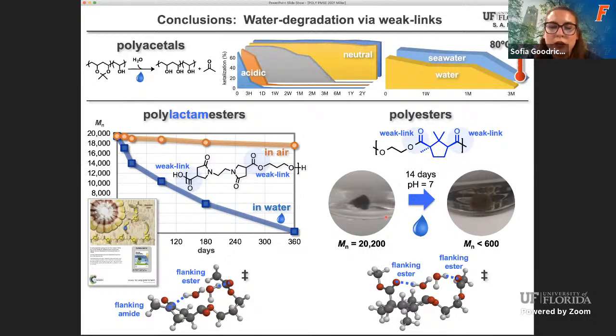I'm just curious what molecular weights need to be achieved in order to display material properties that resemble the synthetic polymers you're trying to replace, and how difficult is that to achieve with these renewable resources? That's a good question, and the bane of our existence at times. We have a general target of 10,000. Now that's a very broad term. It really has a lot to do with entanglement molecular weight. And once you're there, you get Tgs, which are fairly representative. We saw even with our polyvinyl alcohol polymers, around 20,000 going to 160,000, you still see a couple of degree increase in the glass transition temperature.